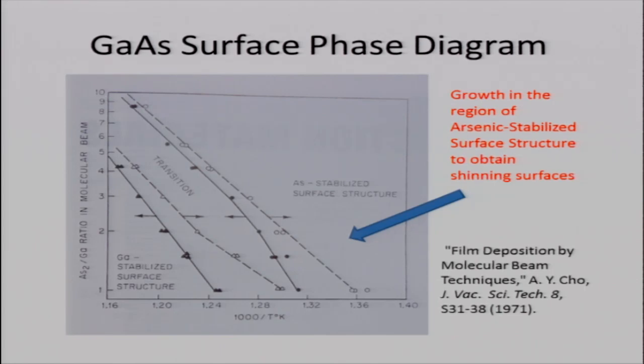I plot the arsenic stabilized surface structure and then the gallium stabilized surface structure on the left-hand corner. As you all know, today, when we grow a shiny, smooth surface, we always want to try to grow an arsenic stabilized surface structure. Why? It's just like John Arthur earlier showed, that any additional arsenic atom just bounces off anyway. Doesn't matter. So as long as you have enough arsenic atoms on the surface, you grow a shiny gallium arsenide surface.